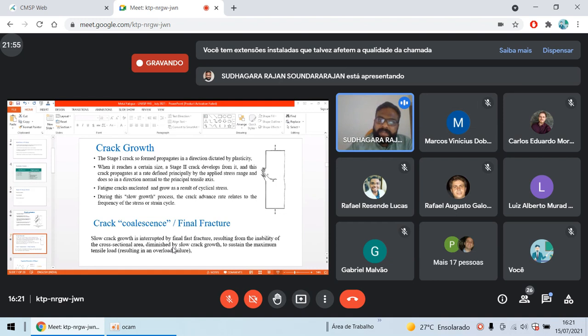We divide the crack growth into two stages. One is stage one, the crack is formed and propagates in the direction dictated by the plasticity. The stage one crack need not be normal to the applied stress. I hope you would have imagined that when a load is applied in one direction, the crack will grow in the perpendicular direction, or normal to the applied load. But stage one will not obey that imagination. In stage one, the direction of crack growth will be dictated by the plasticity of the material. Stage two will be normal to the direction where the load is applied.